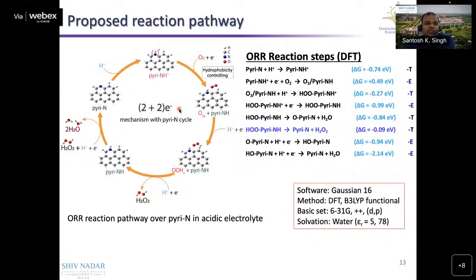Based on this understanding, we have proposed one reaction pathway for this oxygen reduction reaction, which follows a 2+2 electron mechanism in the hydrophobic nitrogen carbon materials. The most important thing to note is that the reaction starts with the pyridinic nitrogen. The most important step comes after the generation of H2O2 as the result of the 2 electron process: this H2O2 takes one proton from the pyri-NH, and it converts to H2O, and further this pyri-NH gets regenerated in the cycle. So if we see here, the pyri-NH is giving a proton, so the pKa plays a role.